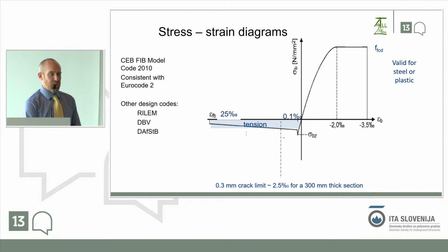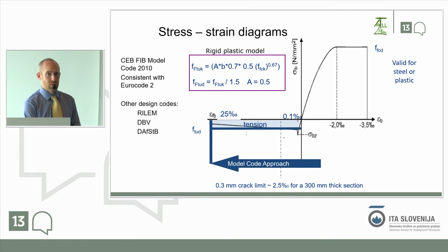So overall, I would say that the best approach is to be using the model code produced by FIB in 2010. It's consistent with Eurocode 2, so that's great. That fits with our normal calculation process, and it's a very well explained method, and you can then create an interaction diagram I'll show you later with the capacity of the fibres added either on their own or together with bars. Still have the question in my head, what numbers can I use? So I'll try and sort of walk you through that. You basically need to be assuming what sort of residual strength you have, and I've called those parameters A and B. If you have test data, you have the answer already. If you make an assumption in a design, obviously you need to test during construction to validate that. But this is sort of an interim, a first guess of what is reasonable.